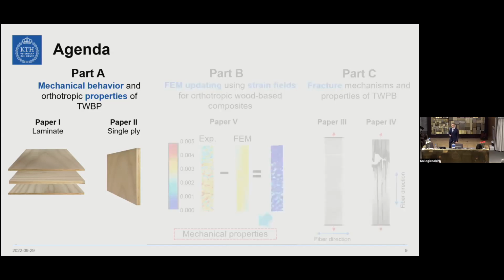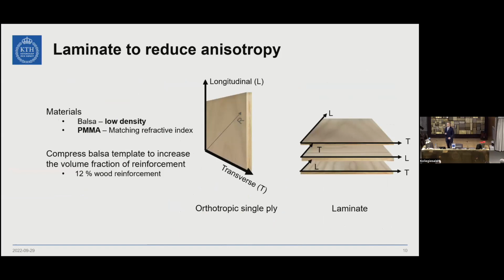Starting with the first one. We did lamination so we can reduce the anisotropy of the material. If you don't do any lamination, the material from a single ply is orthotropic. So by doing lamination, we reduce the anisotropy. In the first study, we used balsa wood, which is low density. It has almost around 95% porosity. And we impregnated it with PMMA.